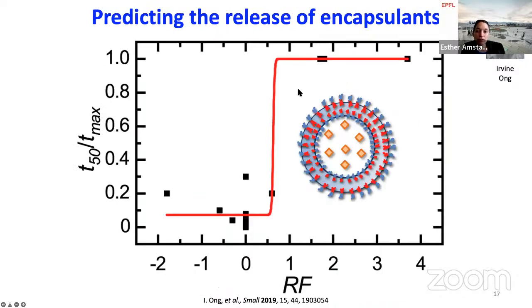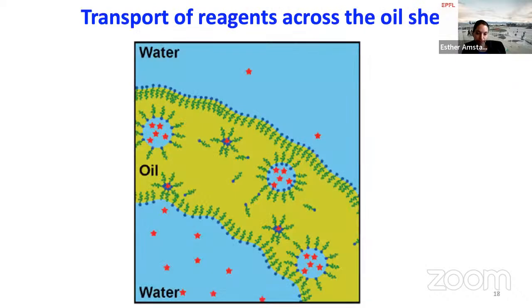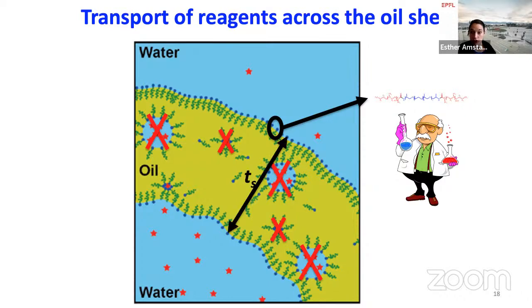This we summarized in this plot here, where the retention factor is nothing else but the product of the average charge of the surfactant and the encapsulant. And as long as that is negative, so you basically have an electrostatic attraction, you get a very fast transport. As soon as that factor is positive, so you have electrostatic repulsion between the two types of molecules, you have nearly no transport anymore. And that is quite a nice way to selectively transport molecules across the oil shells, and also to suppress this transport.